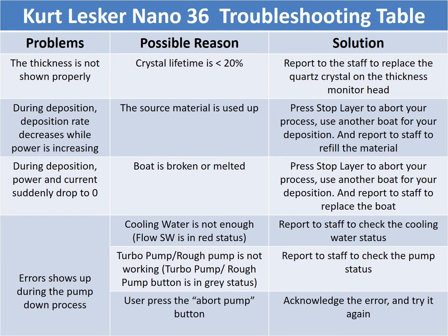This is a Lesker Nano36 evaporator troubleshooting table. It will tell you what to do if you have problems during your usage of this tool. First, if you find the thickness is not shown properly, it may be because the crystal lifetime is less than 20%. Report to the staff to replace the quartz crystal on the thickness monitor head. Next, during your deposition, if you find the deposition rate decreases but the power still increases, it may be because the source material is used up. Please press stop layer to stop your process, use another boat for the deposition, and report to the staff to refill the materials later.